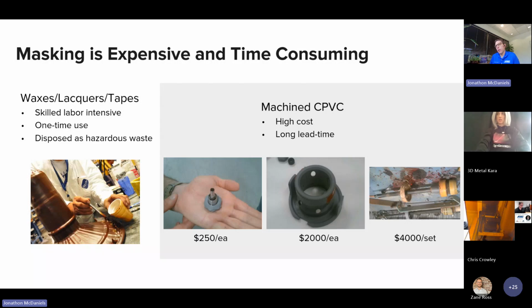So if you've got an operation where you have high variability workload, CPVC is really not feasible for you because the costs are so high and the lead times are so long. A lot of times what we've seen in commercial plating shops is if they have parts come in that have more than 30% of their surface requiring masking, they will actually turn down the job. Air Force doesn't really have that luxury. A part comes in, they've got to do it. So they have to make it work, no matter how expensive it is. One of the reasons they're asking for additive manufactured masking.